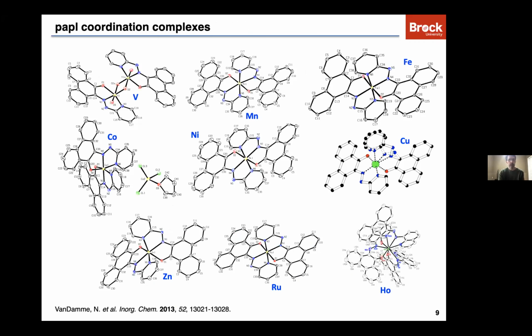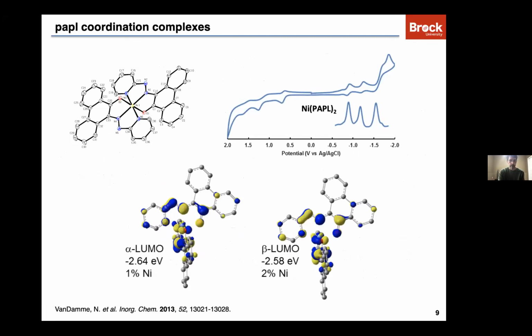We've made several complexes with PAPL and its derivatives. Of course, if you're looking for spin crossover, you would focus on metals like cobalt or iron. So, for example, first look at some properties of basic metal PAPL complexes. The interesting thing with these complexes is the cathodic redox properties are nice, quasi-reversible. You get reduction of the ligands, and the reduction goes into the alpha beta LUMO orbital that was shown here, and this is a nickel complex.